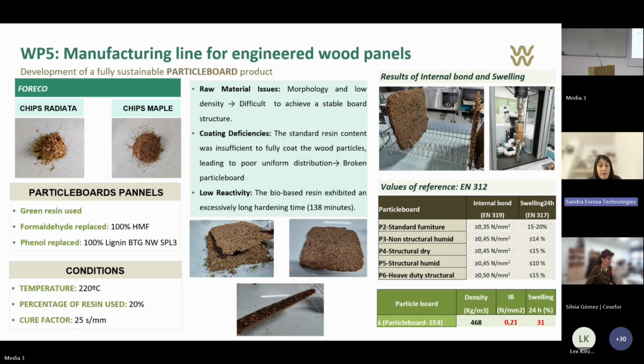With the green resin obtained, but with lower reactivity, using 100% lignin and 100% HMF, we performed particle board panels with wood chips provided by Foreco, maple and radiata pine. The first trial panels were difficult to handle due to structural failure.